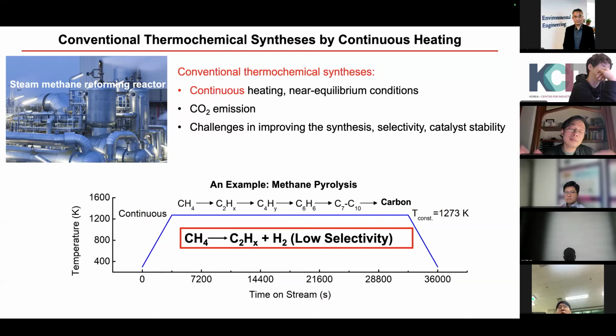But of course, with methane pyrolysis, you can make a lot of interesting products. For example, you have a C2 product, which is much more valuable, but you cannot do that because the time scale of adding one carbon is very, very short, right? It's only like tens of milliseconds. You have to stop it. Otherwise, they can just keep adding carbon, right?